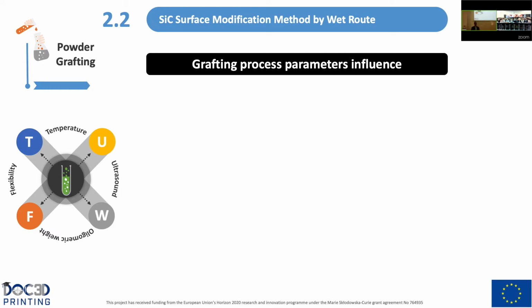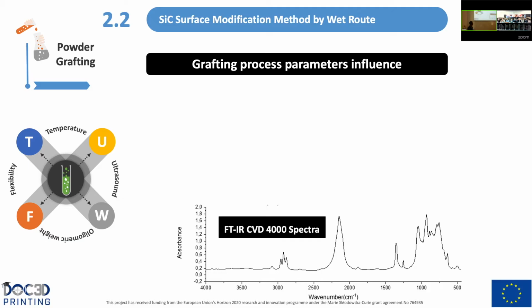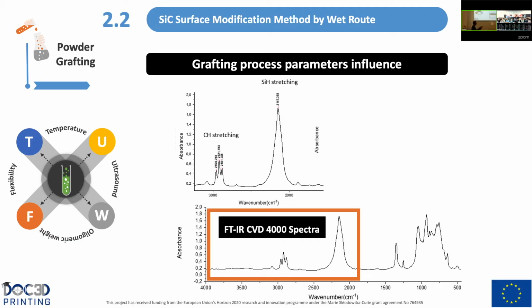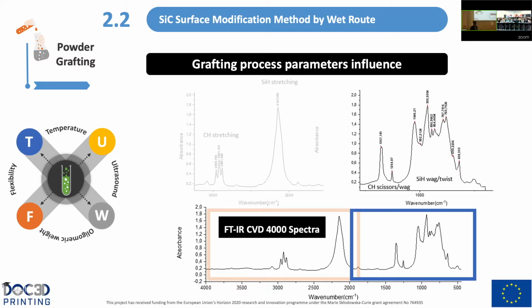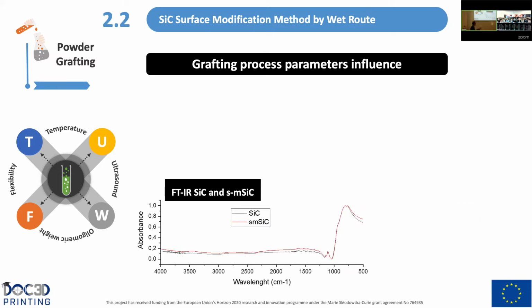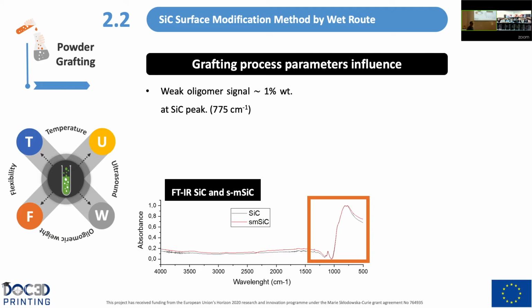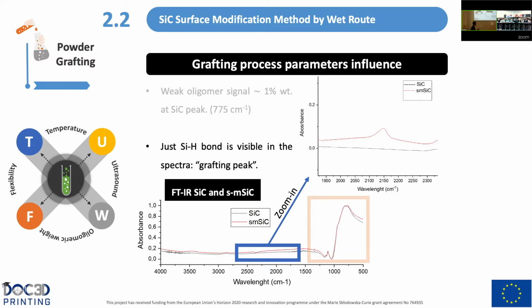Regarding the influence of the grafting process parameters, because for example, we were saying that we were using ultrasound, we were using 60 degrees of temperature for the process. Here we were using infrared characterization to study the grafting efficiency of the process. So regarding the infrared spectrum of the oligomer CVD4000, here we can distinguish two regions. The first one with the CH stretching, and on the other hand, the CH scissor bending and CH bending twist. But if we focus on the infrared spectrum of silicon carbide as received and surface modified silicon carbide, in this region, since we are using a very weak oligomer content, we cannot detect the signal of this oligomer, and yes, we can see the silicon carbide peak. And on the other hand, here, in this part, if we zoom in, we can observe the silicon hydrogen bond. That's why we call this peak the grafting peak, and this peak will be used to study the grafting efficiency of the process.